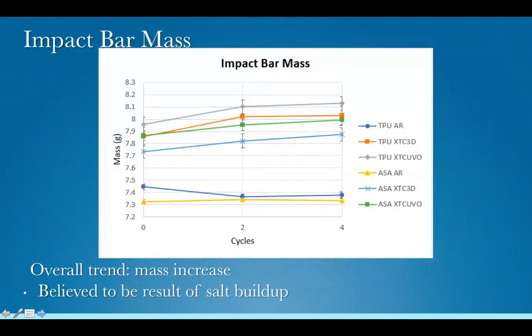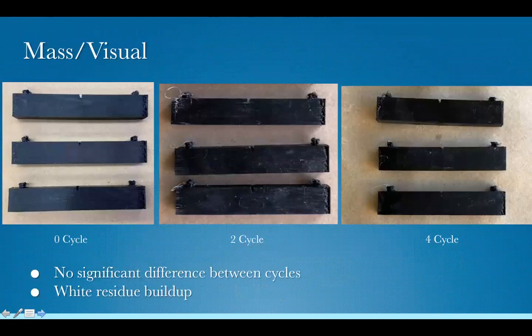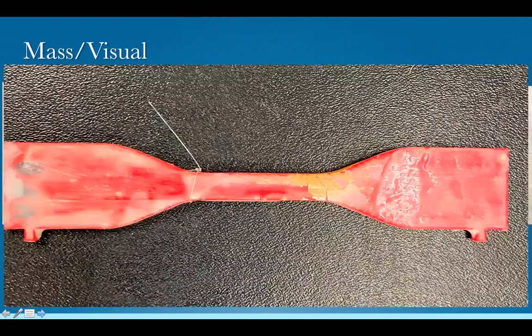The results of the mass data collected show an increase in almost all the samples tested. This is thought to be due to a buildup of salt on the surface or a swelling of the polymers. Further testing is recommended to determine what caused this increase in mass. The samples showed almost no significant visual difference except for a buildup of a white residue on the surface, which is believed to be some of the leftover salt. Another interesting observation was the presence of biofouling on a small portion of the samples. This did not have an observable impact on our data, but is recommended to be further investigated.